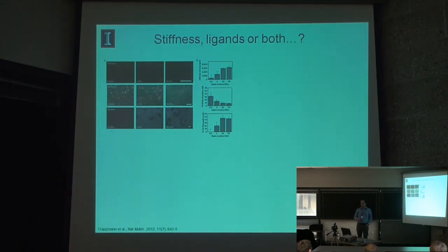This was a big collaboration that was done with Fiona Watt at Cambridge, as well as Wilhelm Huck and Joachim Spatz, a number of these big names. And they published this paper where, using polyacrylamide, and this time they used fat and bone. So fat is the soft tissue, bone is the stiff tissue. And they found that as you increase the stiffness, you get more cells, which is what others have found. But in terms of differentiation, you get a decrease in fat and an increase in bone. So this is expected, that on soft materials, you'll get more fat cell differentiation. On stiff materials, you'll get more bone cell differentiation.